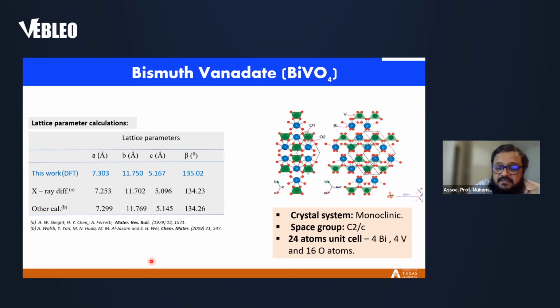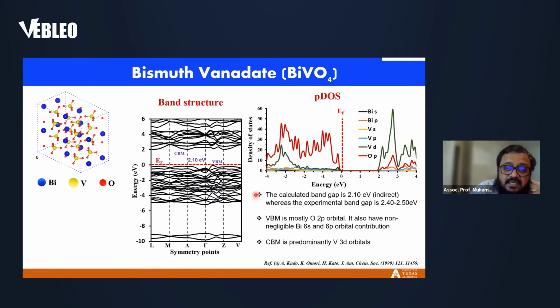So we'll start with bismuth vanadate as a case study for polaron. We have published papers on other materials as well, but today I will talk about bismuth vanadate. It is one of the very popular anodic photocatalysts, and there are plenty of publications in the literature. So this is just an initial check of the lattice parameters from our work versus experimental and other calculations. We see very good agreement. It's just a starting check.